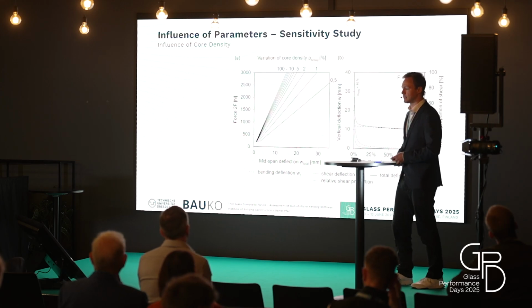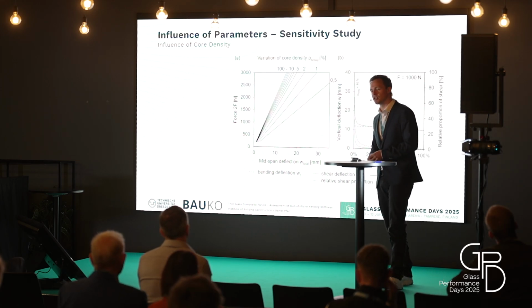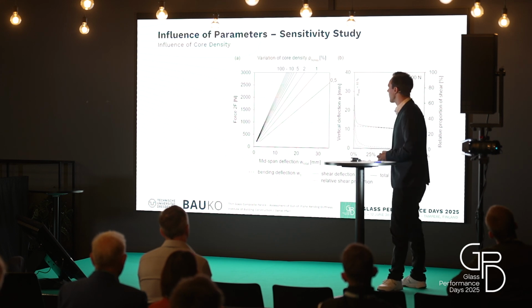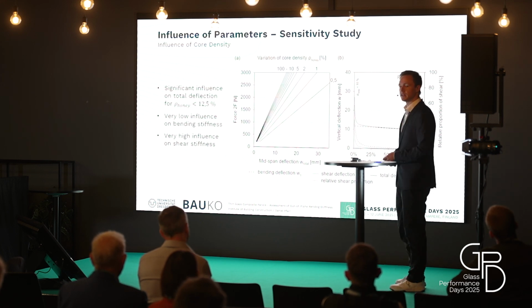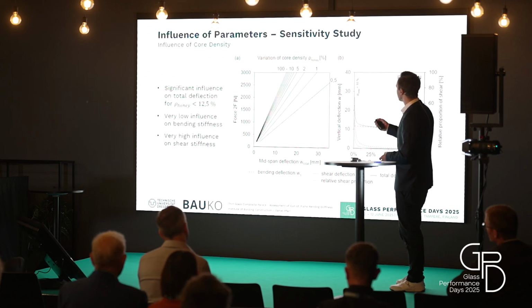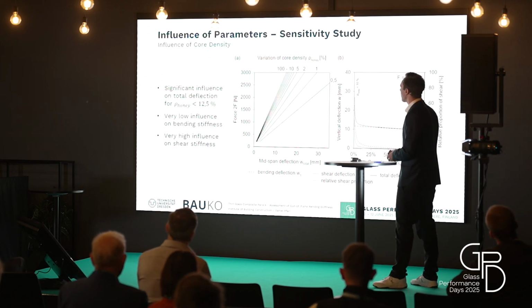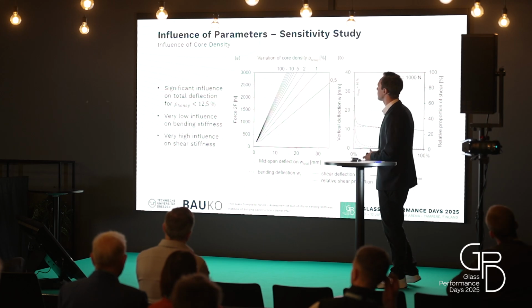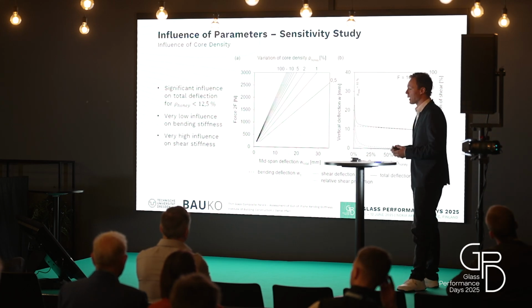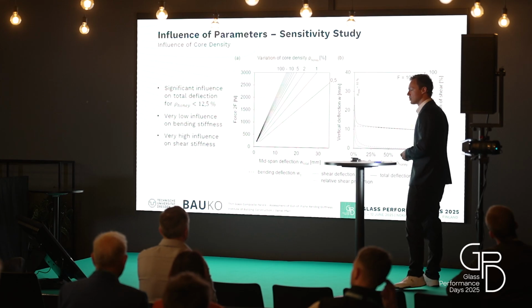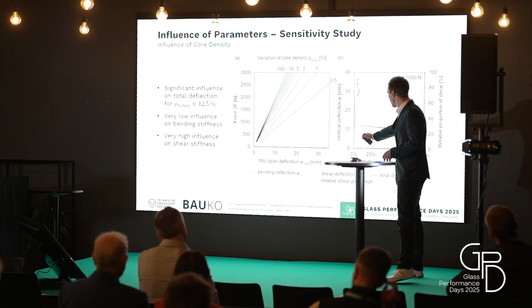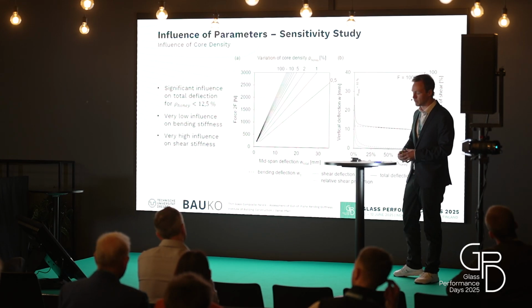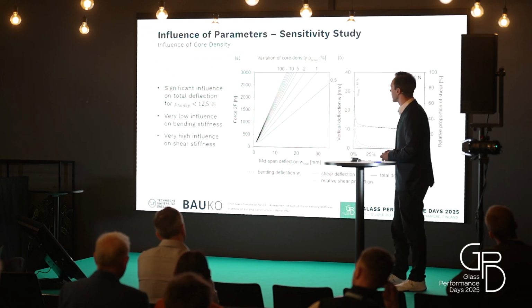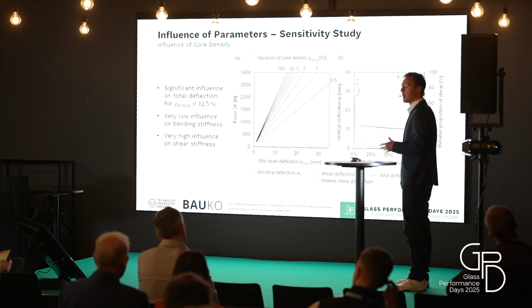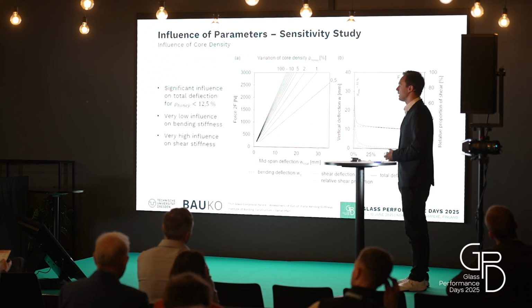The third parameter is the density. Of course, we would like to achieve a very transparent module, so we would like to reduce the core density of the panel. And we have varied it here between 0.5% up to 100%, and we can already see that we have a significant influence on the total deflection for core densities below 12.5%. We can see that we have a very low influence on the bending stiffness, but in that case a very high influence on the shear stiffness of the whole composite.